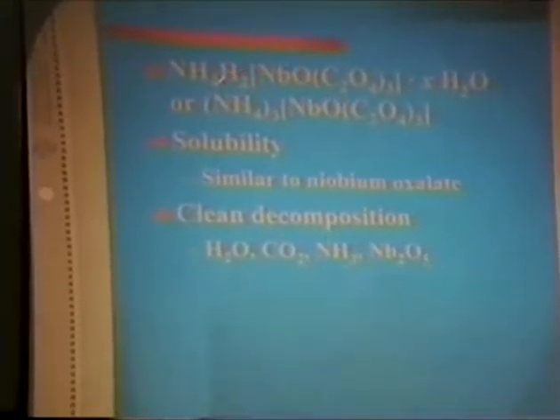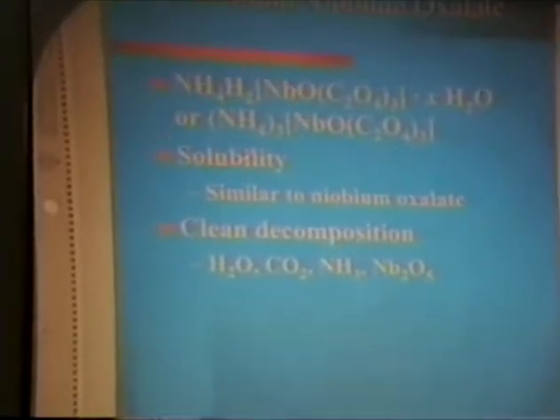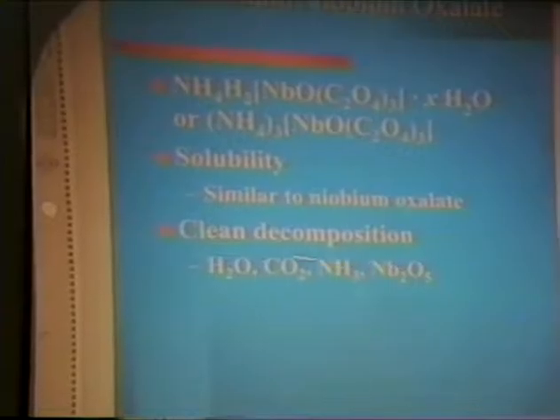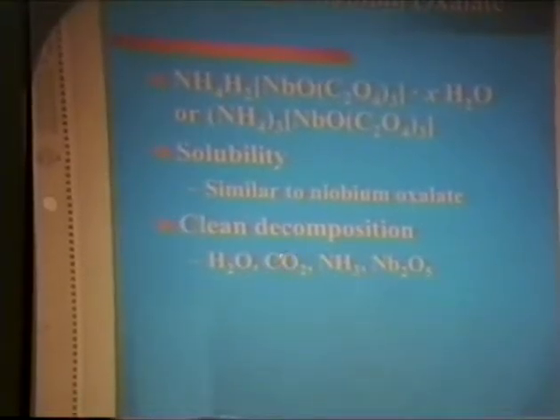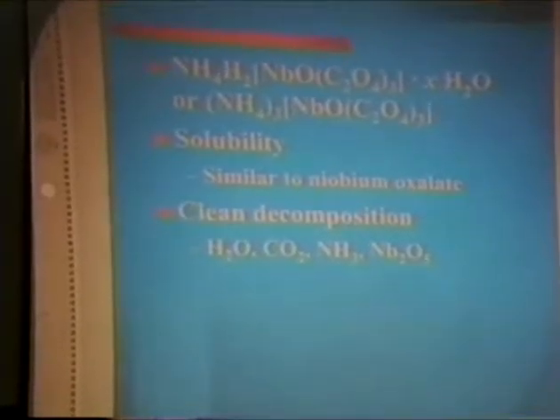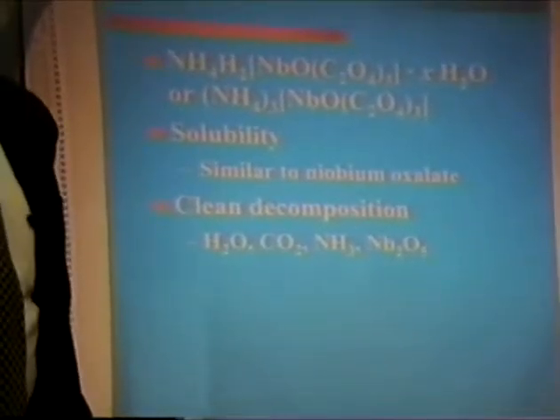The attractive feature of both this and the predecessor is that in calcining, you get clean decompositions. Yes, you may have to scrub some CO2, you may have to scrub some ammonia, but you're not getting chlorine or other materials, and you're not leaving residual metal ions like potassium around.